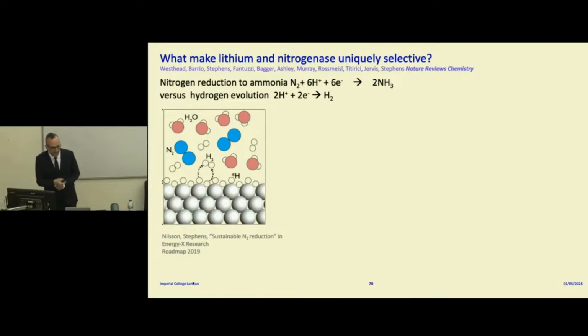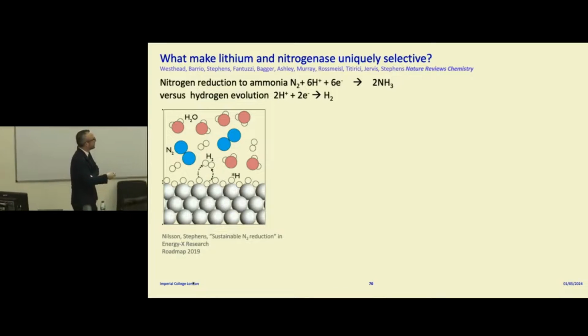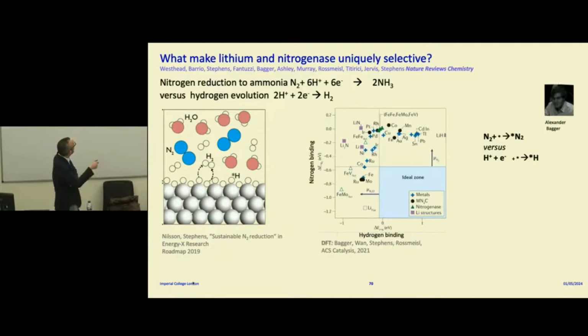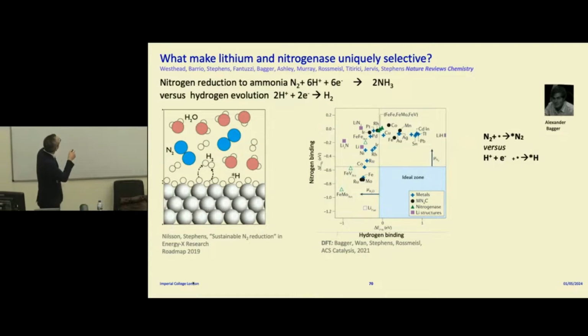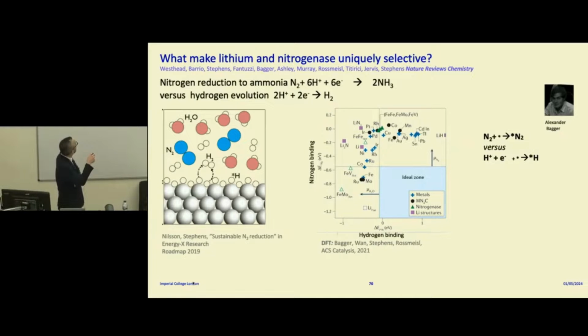So I asked my theorist collaborator, is there something special about nitrogenase and lithium that allows it to work? And the answer is simply no. Even nitrogenase and lithium bind nitrogen strongly, but they bind hydrogen a lot stronger. So if you put lithium or nitrogenase into an aqueous solution, you always get this picture. You get the surface poisoned by hydrogen.